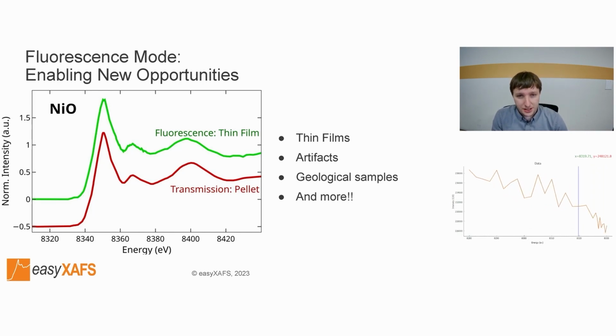There's very good agreement between these two measurement modes. In transmission mode, this nickel oxide thin film sample would normally be impossible because the substrate strongly attenuates the beam and we'd get no signal through the sample. However, in fluorescence mode, we are able to achieve reasonable performance on the order of a few hours.